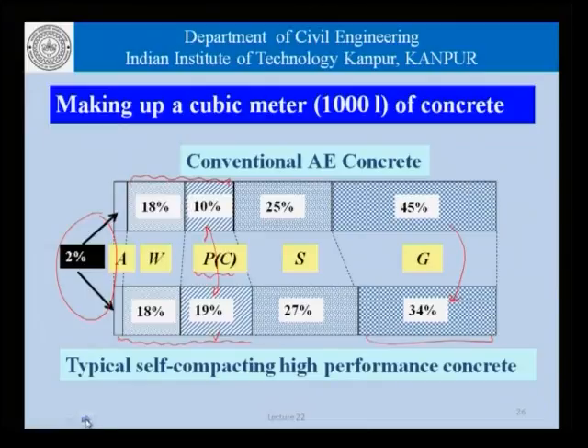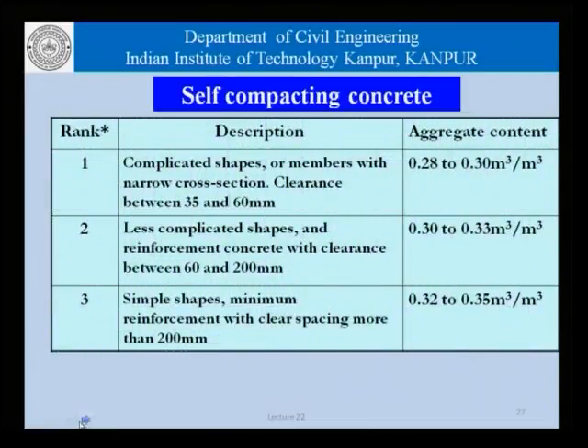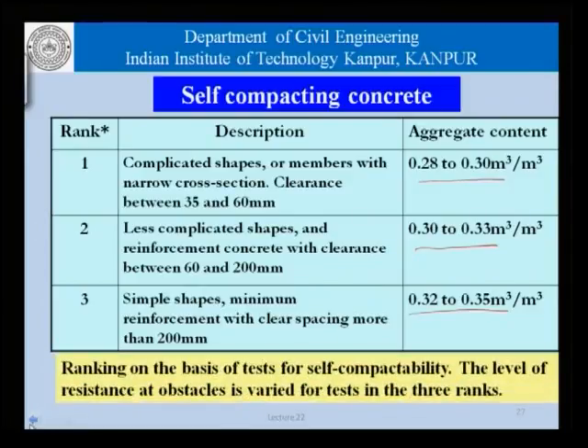and that is something which we had talked about last time, and we had also seen this slide here which talks in terms of limiting the coarse aggregate content between 28 to 35% depending on the complexity of the formwork or complexity of the member in which self compacting concrete is to be cast. This ranking that is given here, rank 1, 2 and 3 for the aggregate content, is based on tests for self compactability, and the level of resistance at obstacles is varied for the tests in the 3 ranks.